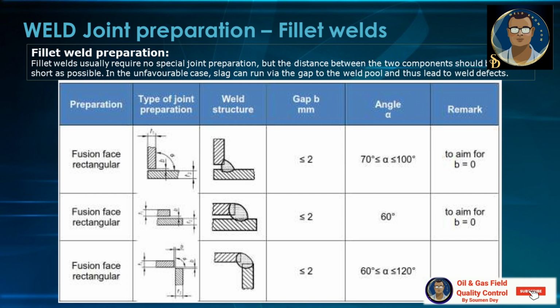Fusion face rectangular. You can see the gap is less than or equal to 2 mm and the angle should be between 70 degree to 100 degree. To aim for, the gap should be zero. Fusion face rectangular. So it will be like a lap welding. The gap less than 2 mm, we should aim the gap to be 0 and the angle should be 60 degree.